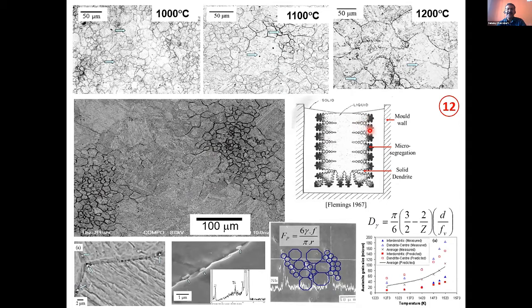And because of that, in regions like this, there are a lot of niobium precipitates. And because the local concentration is also high, those precipitates also remain stable. And as a result, at an intermediate reheating temperature, they can strongly pin down the grain boundaries and the grains become much smaller. Whereas at this location, the dendrite center location, the solute concentration is much less.